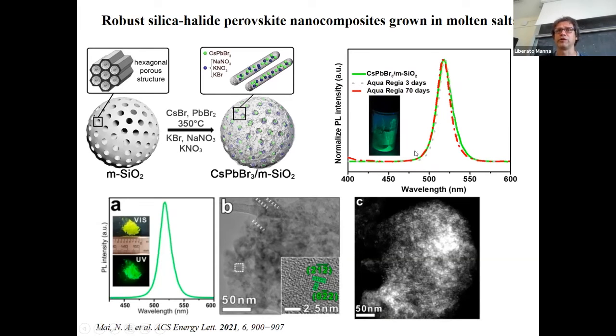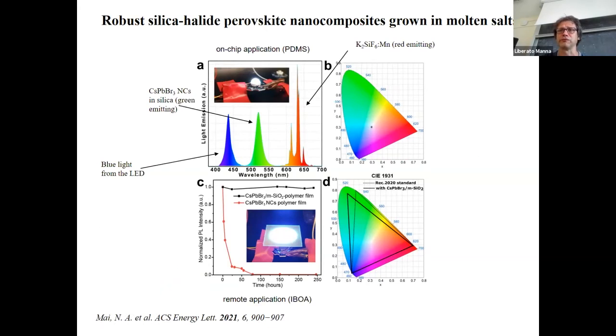And the proof is that you can take this composite and throw it in aqua regia for 70 days. And for the nanocomposite, you still see emission. So they're completely sealed from the external environment. And then, of course, what you can do with these materials is lighting applications. So we tested an on-chip application in which our silica and nanocrystal composites were embedded in PDMS together with a standard red emitting phosphor. And this film was placed on top of a blue emitting LED, and so you get a warm light LED.